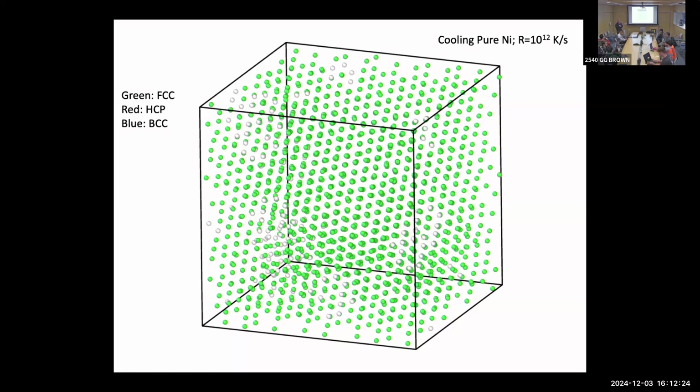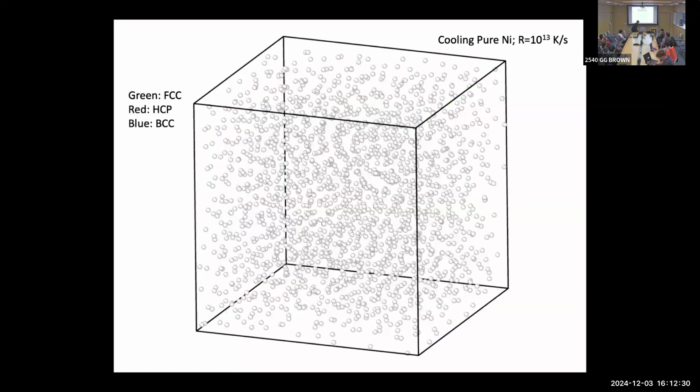I just have a question about the previous simulation. There are several colors. They're all located on a specific particle. Yeah, so what you see on the former slide is everything turned green. What that meant was everything was an FCC-like atom. Ideally, I want to associate an order parameter with each atom. I'll tell you more detail about that, but it's basically what type of local order do I have? How many neighbors do I have? Are they close? Are they in the right orientations? In the one that was cooled fast, most things were disordered, but a few looked like they had some crystal order.